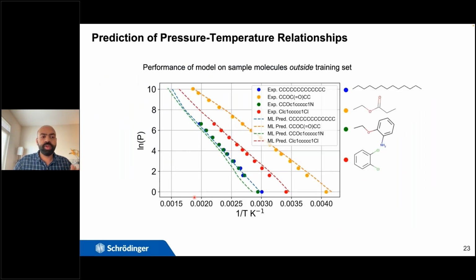And this shows you the performance of this machine learning model for four extremely different types of molecules that were not included in the training set. So here we have the logarithm of pressure on the y-axis and the inverse of temperature on the x-axis, and the dots actually show the experimental data points, and the dashed lines show you the machine learning predictions. So what we see is that the machine learning is able to smoothly interpolate across the different experimental data points, and it's able to predict these experimental values very well, even though they were not part of the training set. And it is able to extrapolate to higher temperatures as well. So this really shows you the power of selecting the right architecture and the right descriptors for training machine learning models for these properties.